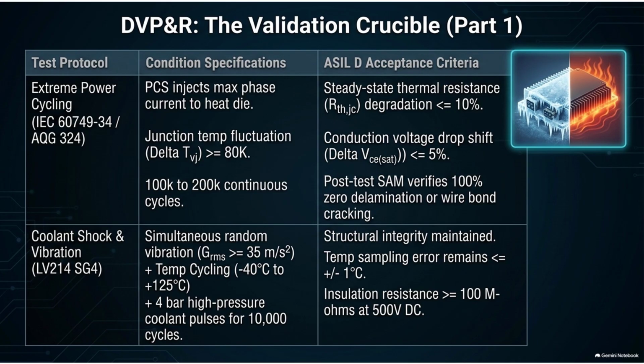To prevent any voids from forming during that advanced silver sintering process, the factory utilizes 100% inline SAM testing on every single unit. SAM stands for Scanning Acoustic Microscope. I had to look this up because it sounds so futuristic. How does sound let you see air bubbles inside solid metal? It uses high-frequency ultrasonic waves, similar to medical ultrasound but at much higher frequencies, sometimes the gigahertz range. The machine fires a pulse of sound down into the power module.